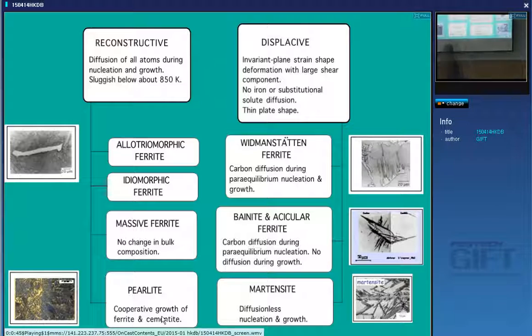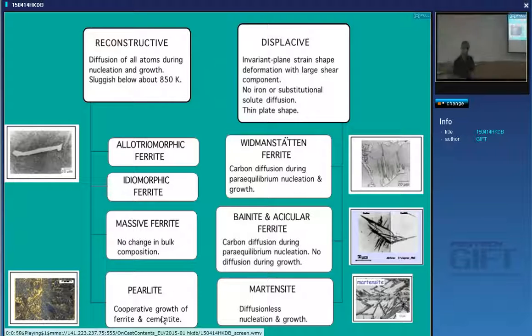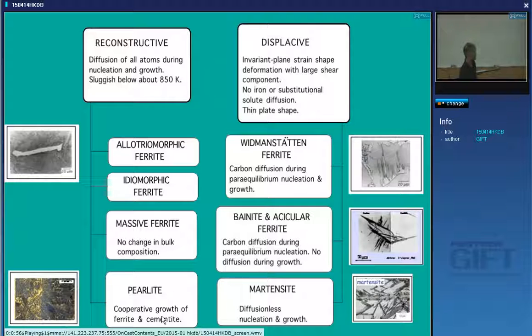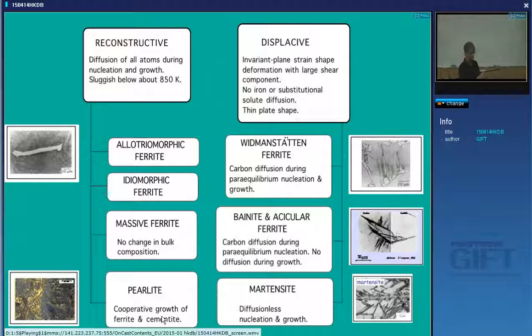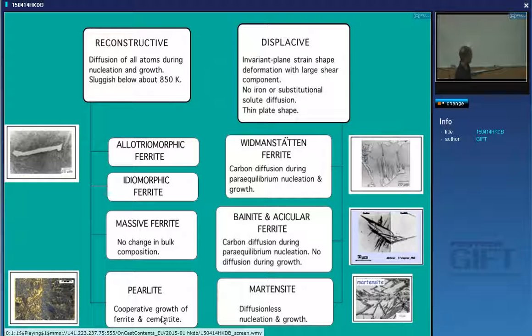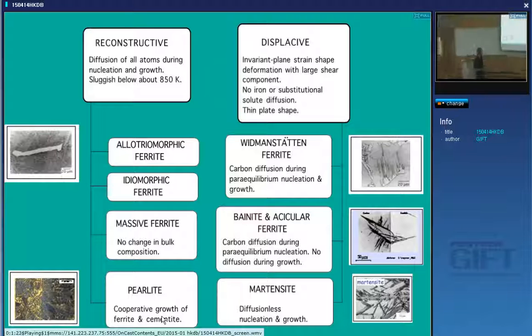Since you allow diffusion to happen, there may also be a chemical composition change during such transformations. The second kind is where you change the crystal structure by a physical deformation — for example, if you have a square pattern you can shear it into an oblique pattern. There's no breaking of bonds, no diffusion necessary, and therefore no composition change. The theory we're going to deal with, although it focuses on martensite, covers all of these transformations. The crystallography of all of these is determined in exactly the same way.